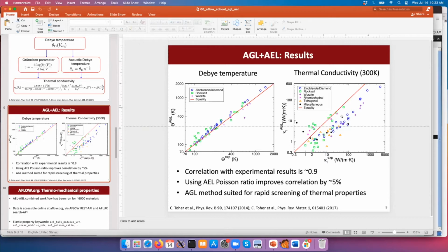Another possibility is that we're using the PBE exchange correlation functional. This tends to underbind, so it tends to make the bonding too weak, and that in turn will tend to result in an underestimate of things like the thermal conductivity as well. You'll see that the bulk modulus is underestimated, and various other quantities are underestimated, and in particular at longer distances it will underestimate even more, which will probably make the energy volume curve look more anharmonic than it otherwise would be.